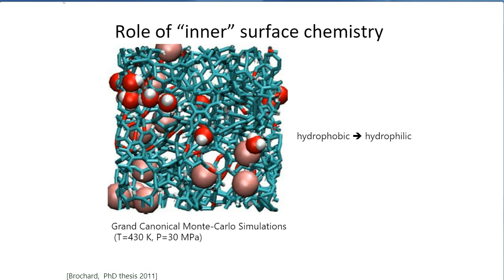We can go from hydrophobic to hydrophilic depending on the amount of those defects. The disorder has two components: what I call topological disorder — everything that is not purely sp2 carbon — and chemical defects like oxygen-containing groups. Altogether, that clearly drives the adsorption. But if we are to provide electrons to this porous carbon in a supercapacitor device, we expect those defects will play a role because they will accumulate charges or deficits of charges.